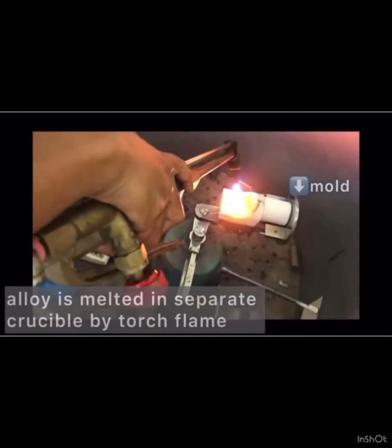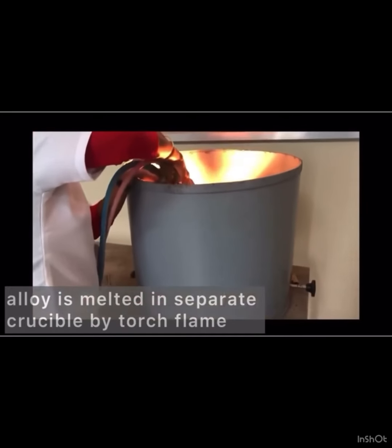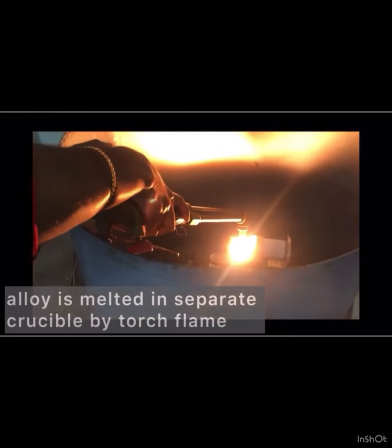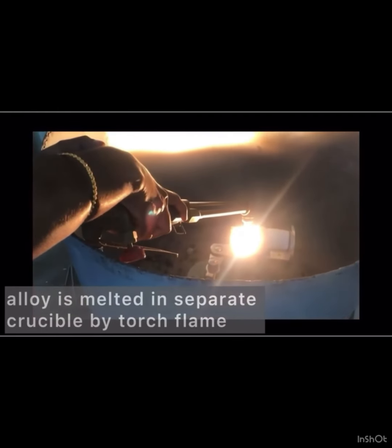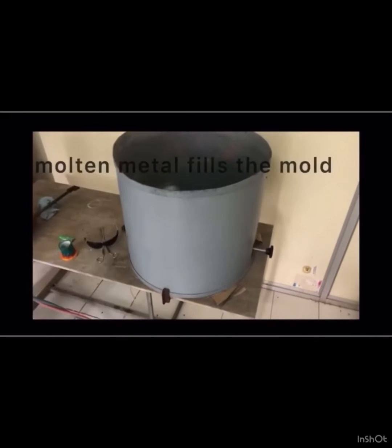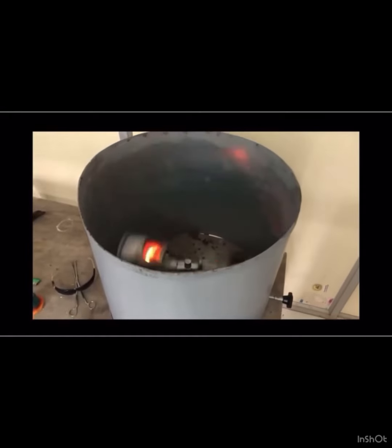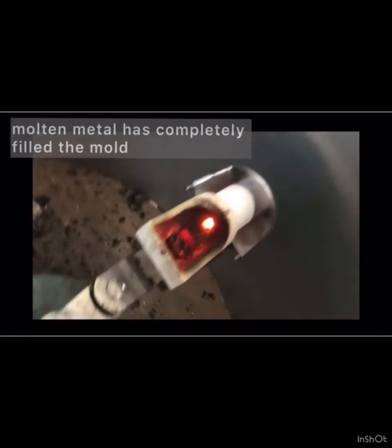The mold has been placed there, the alloy is placed in the crucible former, and then the torch flame is used to melt the alloy. The reducing zone of the flame is kept right on the metal pellets until it melts completely. Once it has melted, the spring is released and the molten metal enters the mold owing to this action. You can see here that the crucible where we melted the metal is empty now and it has completely entered the mold. The mold is then removed from the machine and it is quenched in water.